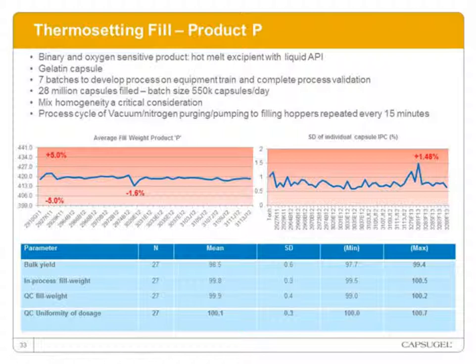This next slide shows another thermosetting fill. In this instance, we have a liquid API, which is in a hot melt excipient. And we, again, transferred this process from a client. We used 7 batches to develop the process on the equipment train and complete the process validation. Up to 28 million capsules have been filled, and with this process, we were able to fill about 550,000 capsules per day. The interesting point here is that mix homogeneity is a critical consideration for this product, so we need to ensure a very good mix of the liquid API with the hot melt excipient.